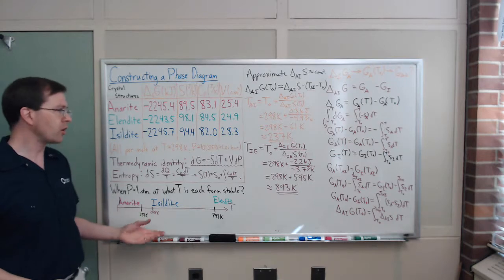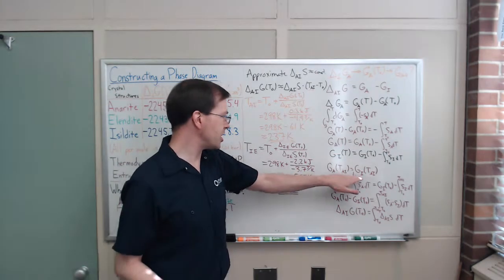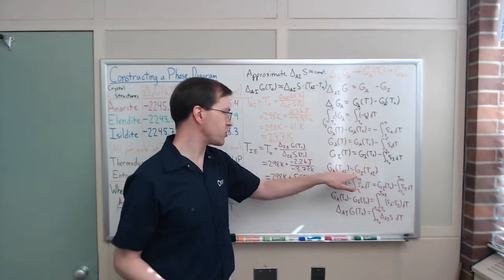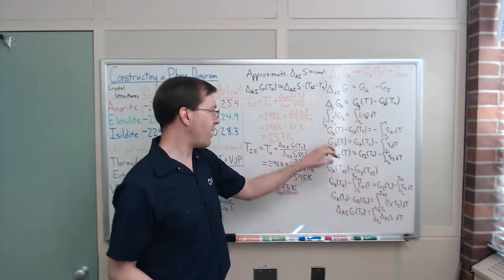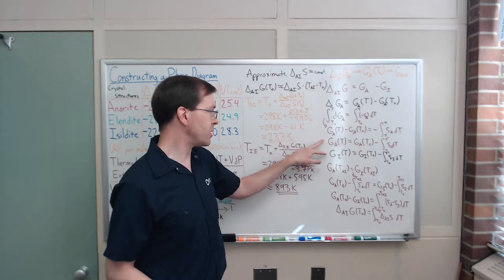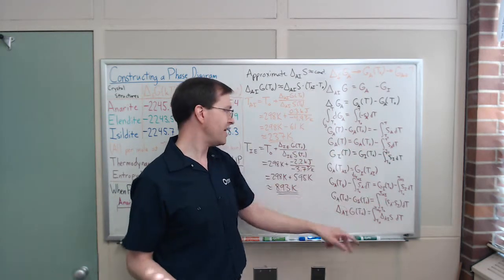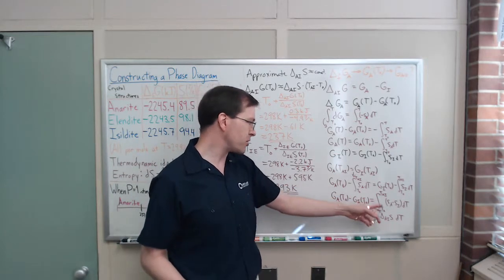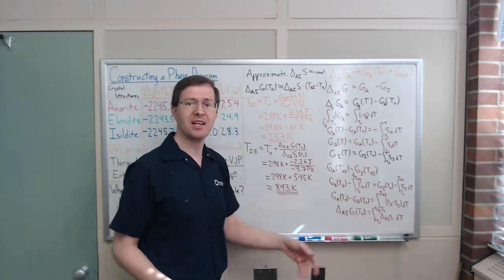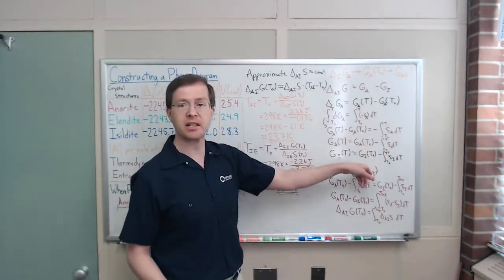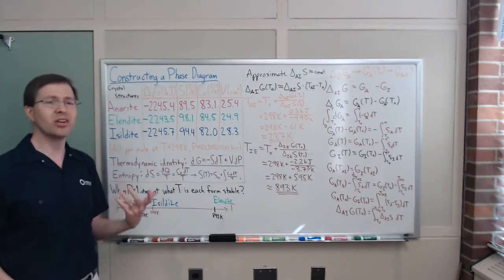You just look for where you set the two G's equal. Find your specific temperature where those two G's are equal. You have four functions for Gibbs free energy as a function of your initial Gibbs free energy and an integral of entropy. And setting it up so you're doing an integral of the difference of entropies is a little bit more reliable than integrating and then pretending that each entropy is a constant on its own. It's still not perfectly constant.